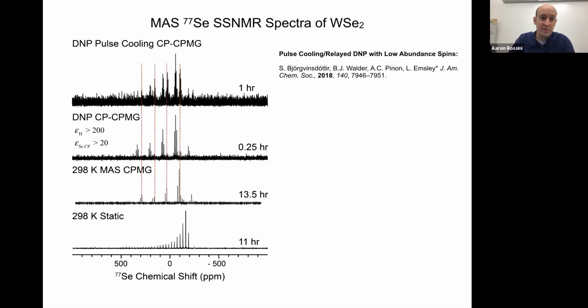Now, one interesting observation here, if we actually carefully look at the peak positions that we see in our CP-CPMG spectrum, they don't actually match up well with what we see at room temperature. If we do the pulse cooling experiment recently discussed by Emsley, and Sneddon talked about this in a nice lecture in one of the early DNP webinars, where you give time for selenium spin diffusion to occur, we actually see a second set of selenium peaks that match up with the bulk selenium emerging.